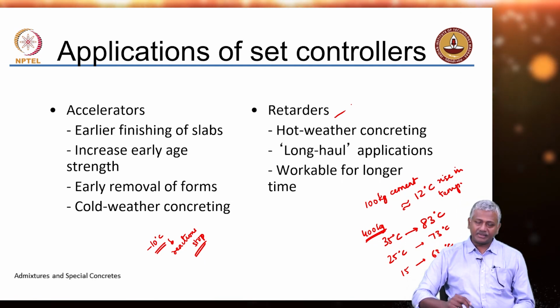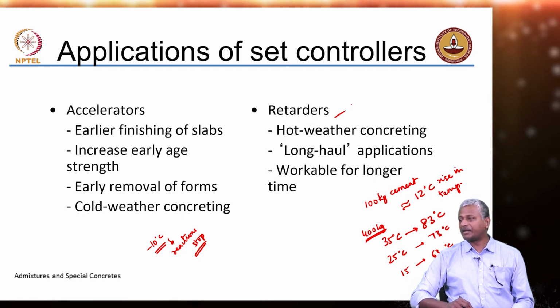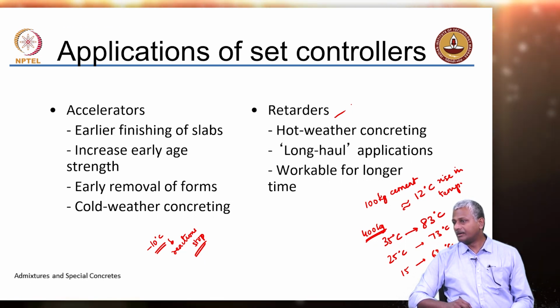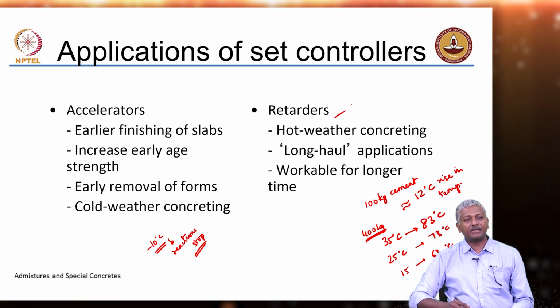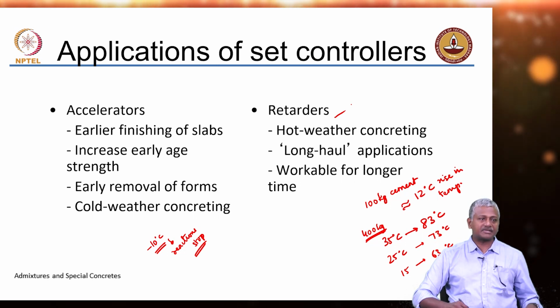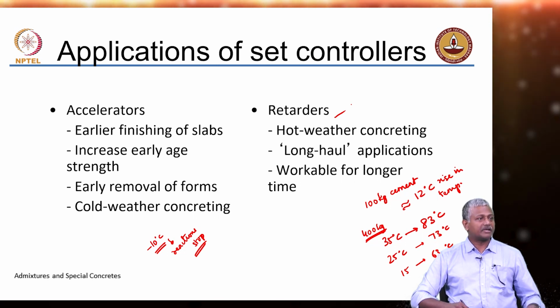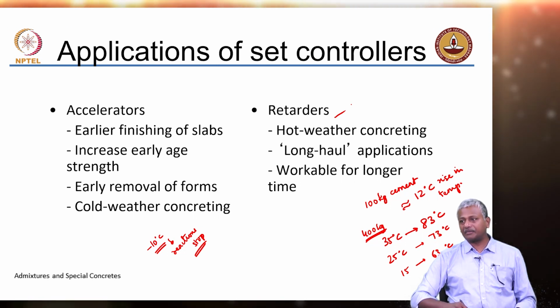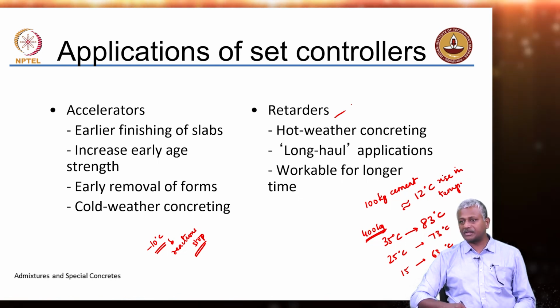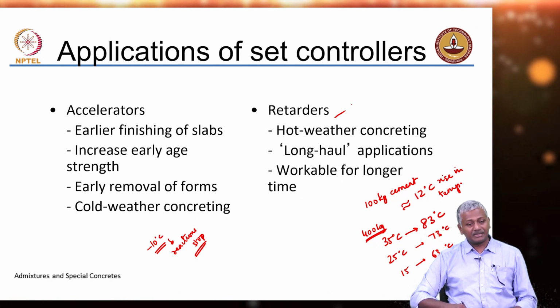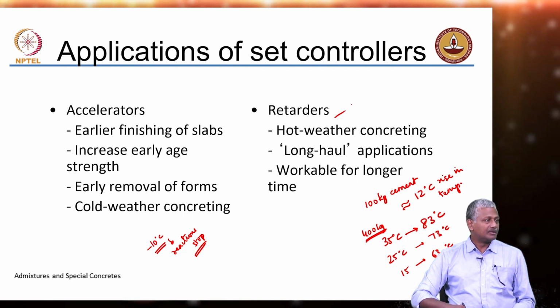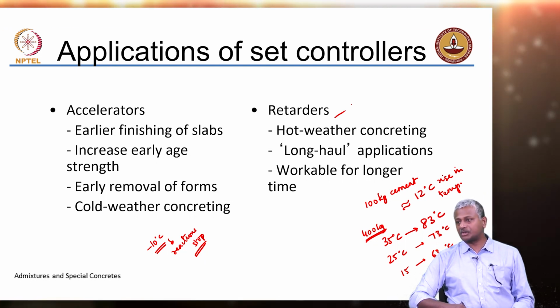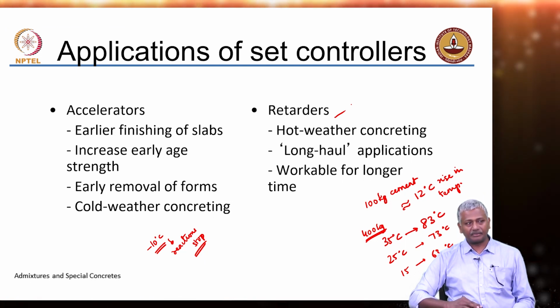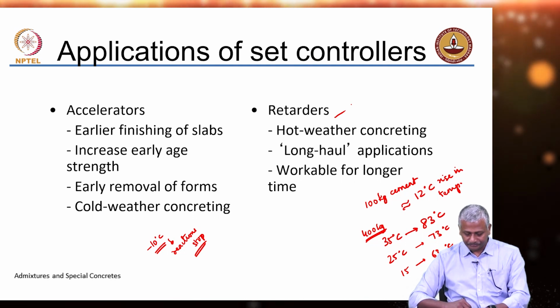There are actually other instances. For instance, you have to supply concrete on a hill, right, and your nearest batching plant is somewhere far away. So, imagine the time it takes to do the climbing to really get to the job site to really deliver your concrete. In such cases, you definitely need retarders to ensure that the concrete does not start setting while it is supplied to the job site.